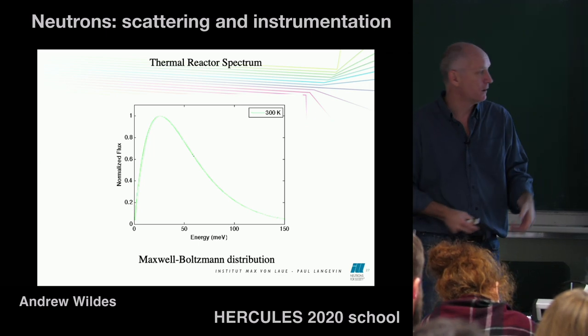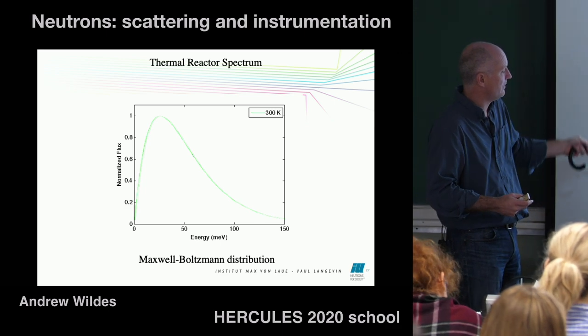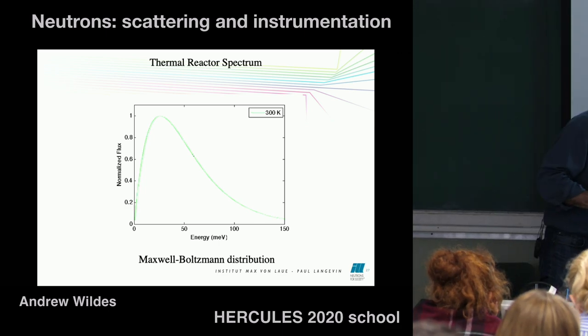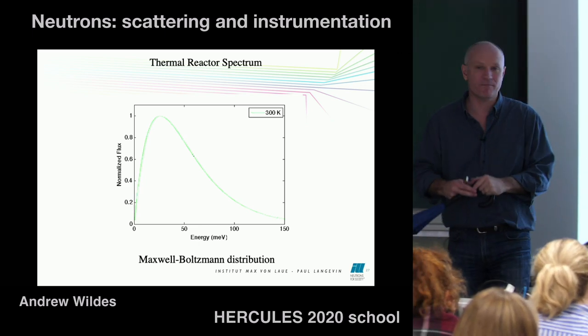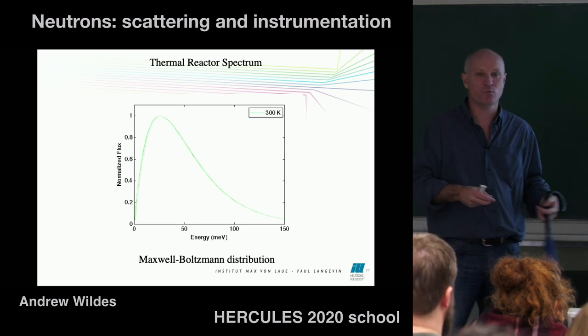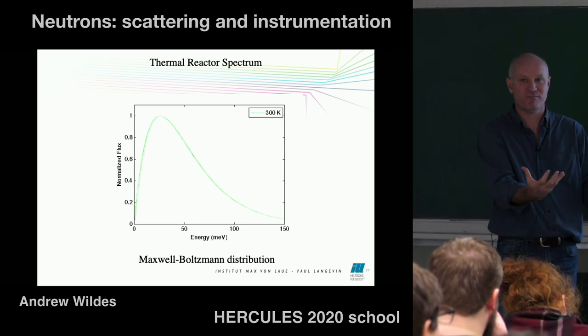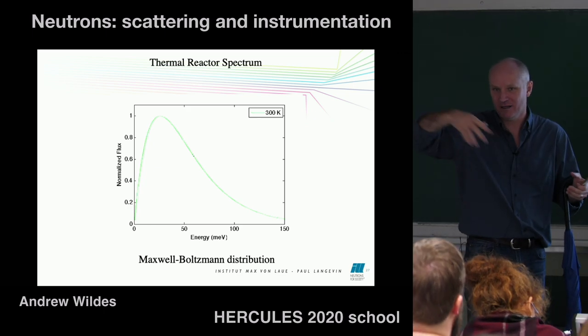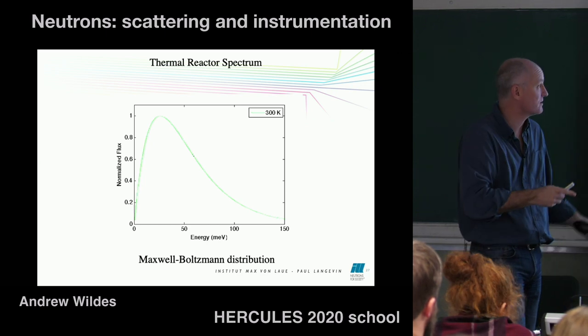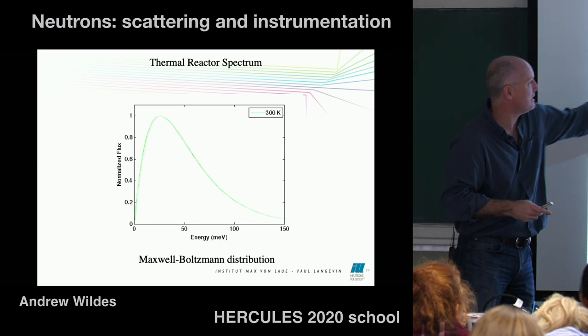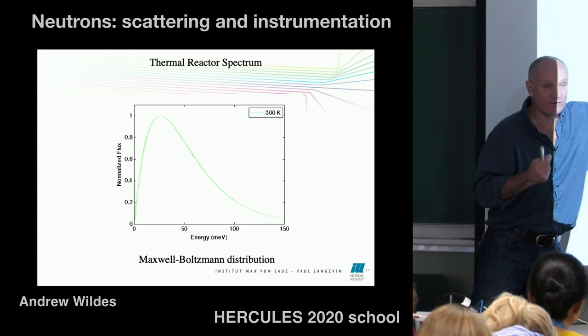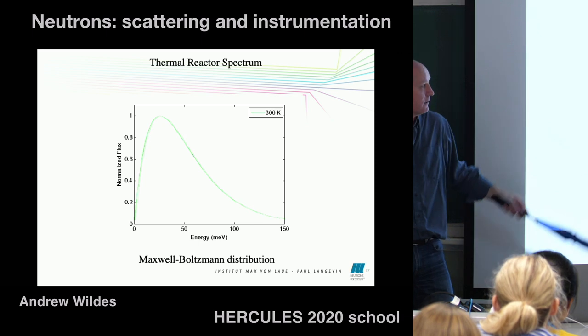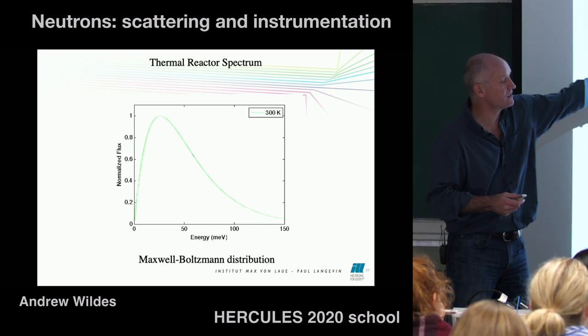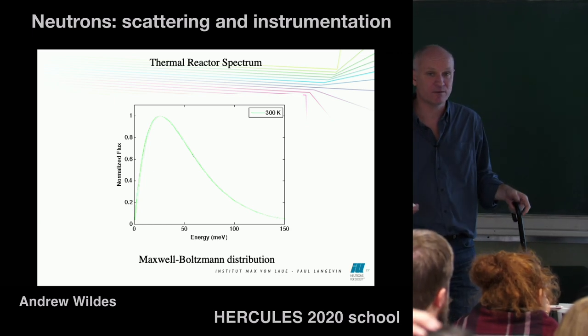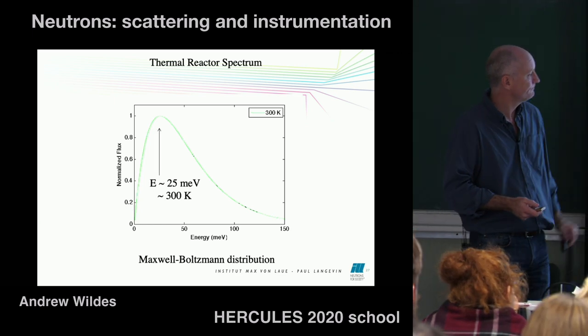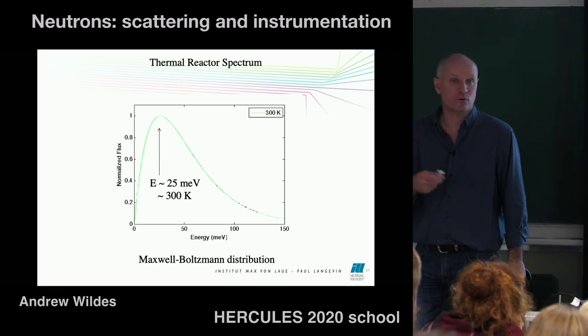It's about 300 Kelvin. If you look at the intensity or the flux coming off that part of the moderator as a function of energy here, you get this very classic type of curve. It's called a Maxwell-Boltzmann distribution. It's the same sort of curve you would see from what we call a black body radiator. So if you heat up just a piece of metal, and you looked at the heat energy coming off, it would have the same type of distribution as this. And the maximum here, that's the energy equivalent to the temperature of what you keep it at. So in a thermal reactor, like the ILL, the peak in this is at 300 Kelvin, which is room temperature. That's the temperature that we keep the moderator at. Right, there you go. So it's about 25 millielectron volts, which is about what we need for neutron scattering.